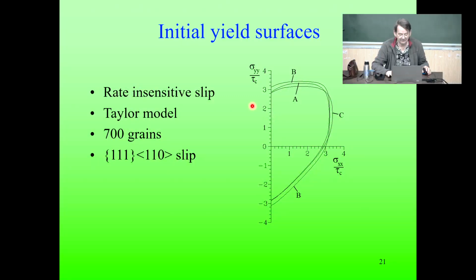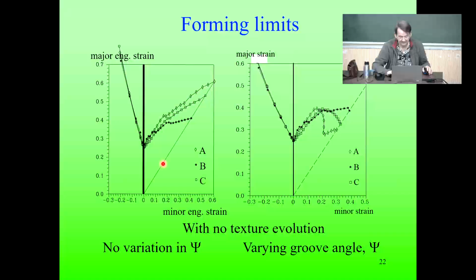Now, the yield surfaces were calculated to show, because basically what is happening is that the stress state is moving on the yield surface. So, for example, biaxial deformation, we start here for the sheet and also for the groove, but for the sheet it is going to move in this way by hardening, but in the groove the stress state is moving down into the plane strain state, and when it is reaching that position, then deformation is fully localizing in the groove. So here, 30 years ago, the Taylor model was used, rate insensitive slip, 700 grains, and then this was assumed for the slip families in aluminum.